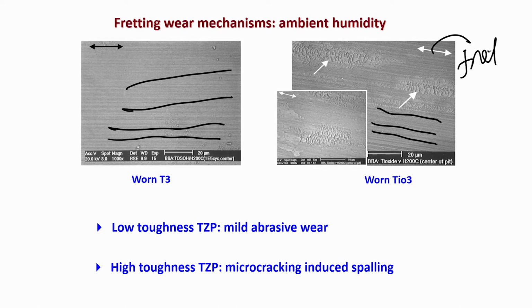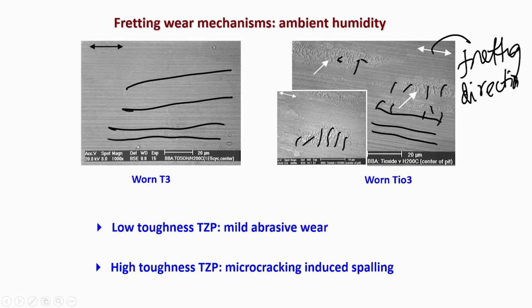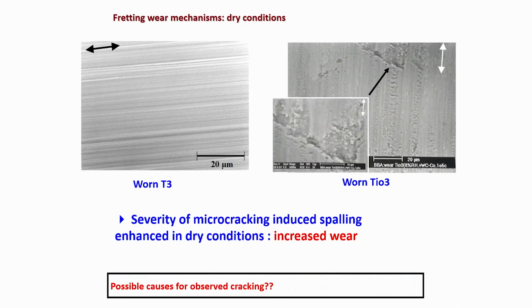This is your fretting direction, but you will see some additional observations. If you look very closely at this particular image, there are some microcracks, and these microcracks are aligned perpendicular to the sliding direction. When these microcracks are aligned perpendicular to the sliding direction, what will happen? These microcracks can grow very fast, because in the perpendicular direction there is also a tensile stress field, and the tensile stress field can drive these cracks and lead to measurable crack growth, and that can lead to microcracking induced spalling. So, microcracking induced spalling is the major culprit for the low wear resistance of high toughness tetragonal zirconia polycrystals.